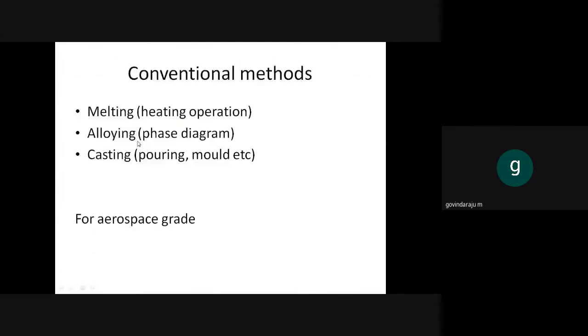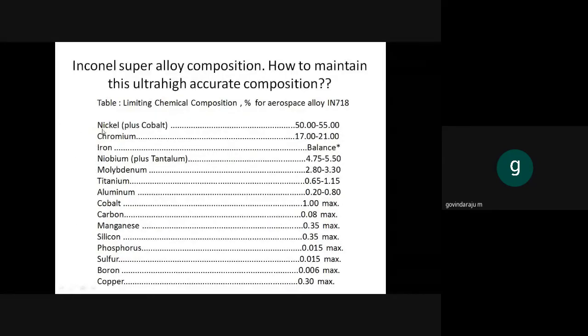If you do a simple casting like this for this alloy, that's all. There are some 13 different elements. Each one needs a different crucible and different atmosphere. How to make it? And just see the composition. You have to maintain a tight composition. For example, I'll give only one example, aluminium. Here it is given, this is a textbook range of 0.2 to 0.8, but let us say people stick to only 0.6%. Everybody will use only 0.6%.